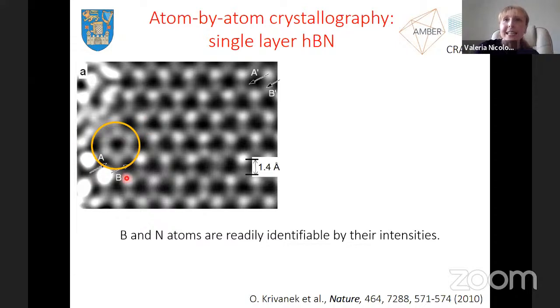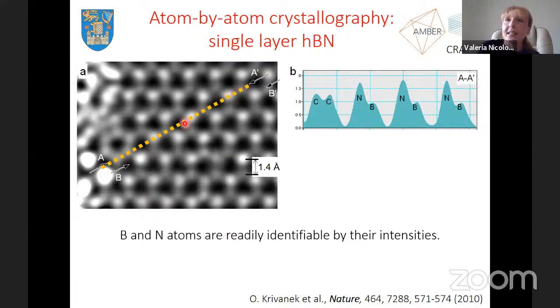For example, if you look at the intensities of these atomic species in this hexagon, you could see that this intensity here is stronger than the boron atoms, but it's lighter than the heavier nitrogen atom. So the atomic number was somewhere in between. If you take an intensity profile and you track the intensities of all these atomic species going from here to here, you see that it is boron, nitrogen, boron, nitrogen, boron, nitrogen, until you actually hit these atoms here, and their intensity is intermediate. And you can assess with 99% certainty that these are carbon atoms. So the sonication really made defects, and these defects were filled by carbon atoms that were probably coming from the solvent that we used. There were other deviations. For example, this is an atom here that is much brighter than the nitrogen that we could see here.